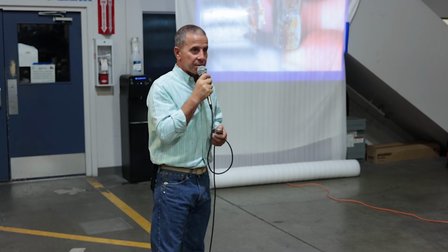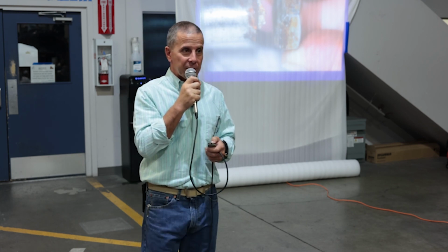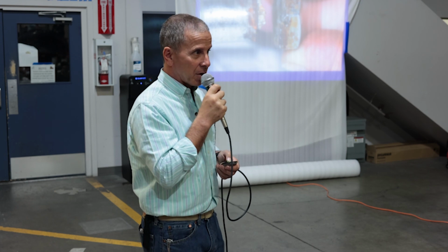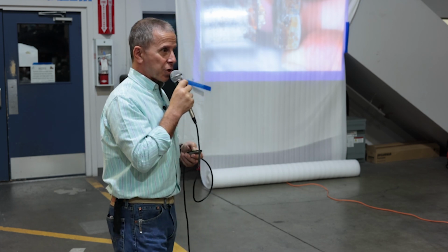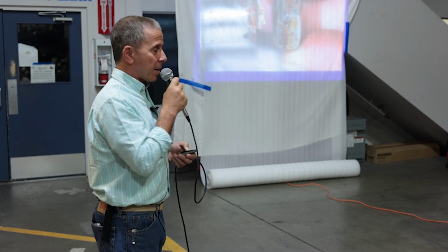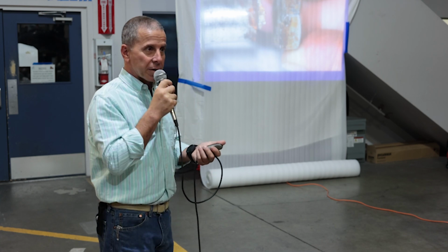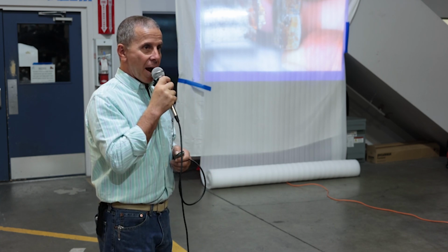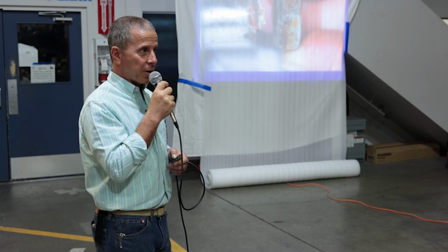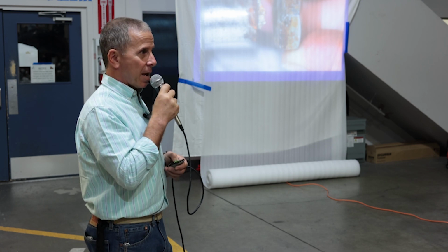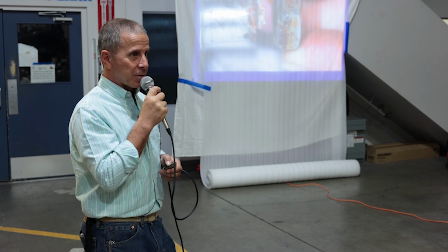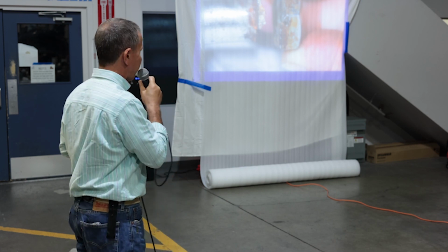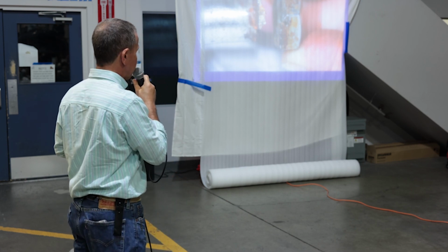Another stress corrosion cracking scenario for stainless steel. You can see the head of this fastener actually separated from the shank, probably after being torqued. There's some microscopic cracking between the head and the shank. Water penetrated into those cracks and exacerbated that situation, eventually causing that fastener to fail completely.